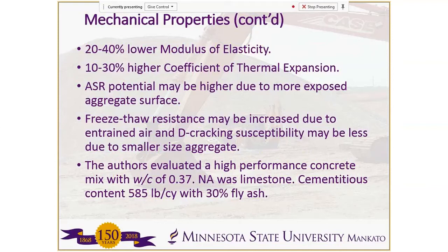Most of the experiments and most of this data were done earlier on. As I mentioned, this was done mainly in the 1980s and so on. Concrete mix designs have changed quite a bit since then. So we decided to evaluate a high performance concrete mix with a relatively low water cement ratio of 0.37. For the natural aggregate, we used limestone aggregate, and cementitious content was 585 pounds per cubic yard, and we used 30% fly ash substitution.